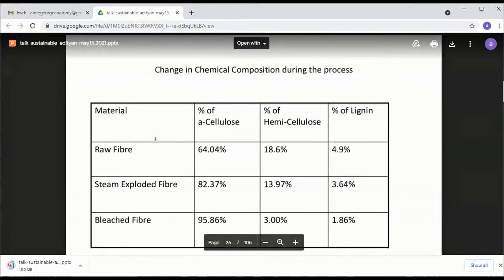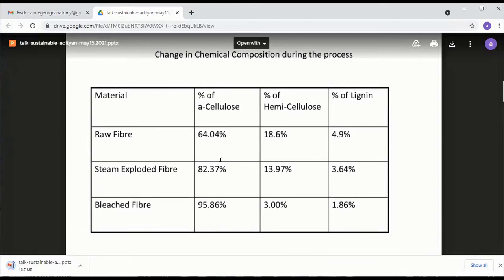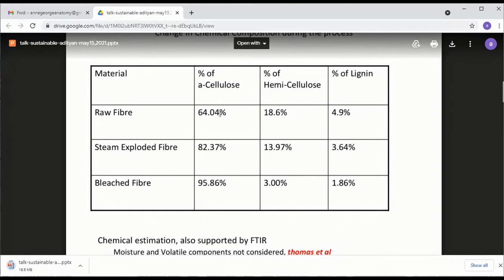And let me show you the dynamics of the enrichment process. You see, when you collect raw fiber from the plantation, the cellulose content is 64%. Hemicellulose is 18.6 and lignin is 4.9. But when you do this chemical treatment by steam explosion, bleaching, the amount of cellulose goes up. You get 95.86%. And you remove hemicellulose and lignin by chemical hydrolysis. And you get really very high quantity of nanocellulose.